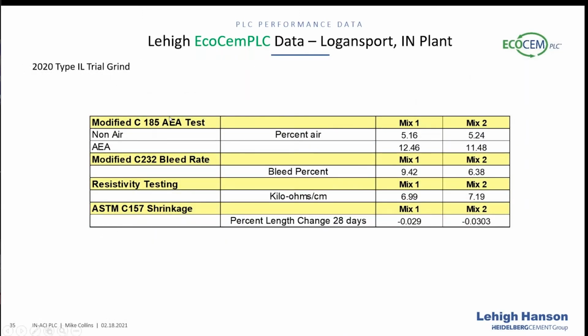So let's look at some of the other things we did. To measure air performance, one of the things we do is there's a test called C185. If you see a mill test, we talked about this in December, the air content data you're getting on that is not concrete air. That's not entrained air from a concrete. That is entrapped air that's measured in a cup of mortar, a 400 milliliter brass cup. What we've been doing for years in our lab is taking that cup, repeating that mix and adding a very minute dose of air entraining admixture. Then we look and see what the difference is. Does it generate air? Does it generate air predictably? Also, by the way, it's just a great test to use for fly ash. I think personally better than the foam index test, but that's another talk as well.